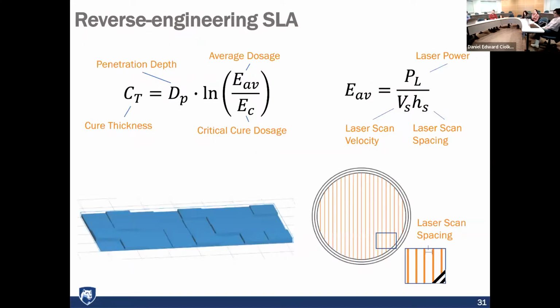So one of the things that we were interested in with 3D printing by SLA was monitoring both what we call the critical cure dosage and the penetration depth. So the photons, imagine you have this liquid and you shine a light on it. The photons will travel some distance into the liquid, and then they'll meet one of those molecules that absorbs them, and then polymerization takes place. So the distance that it has to travel before it finds one of those molecules is called the penetration depth.